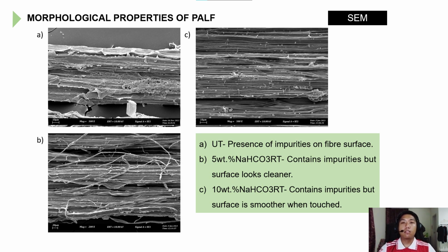Next, we have the morphological analysis of the pineapple leaf fiber. So these are the morphological properties of the fiber surface. As you can see, in the untreated fibers, there are impurities in the fiber surface. From figures B and C, which are 5% and 10% sodium bicarbonate at room temperature, there are still impurities in the fiber. However, we can see that the fiber is slightly cleaner compared to the untreated fibers, and when I handle the fibers, they feel a lot smoother to the touch.